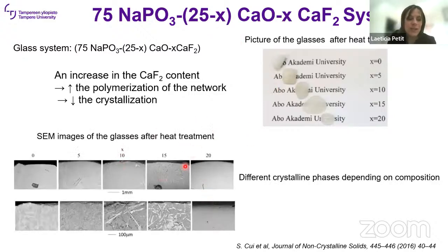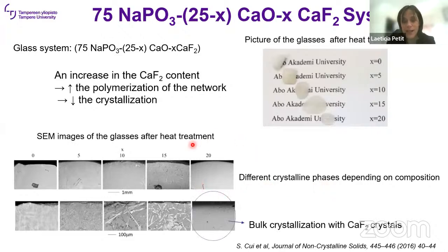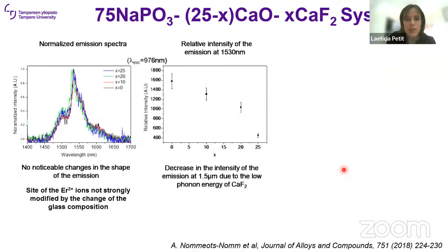So we used the SEM to try to understand what's going on. And then we have, of course, different crystalline phases growing in the glasses. And then we found that the glass with a large amount of calcium fluoride has this bulk crystallization with calcium fluoride crystals. So, which means that it's probably a good candidate for upconversion application.